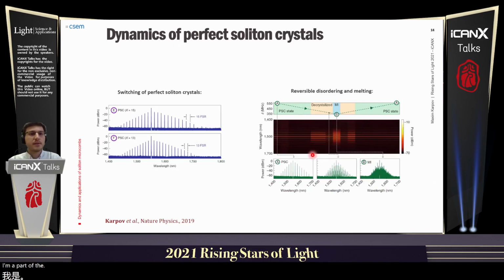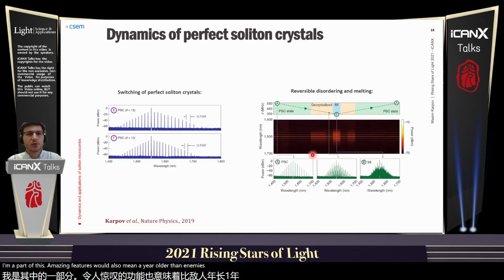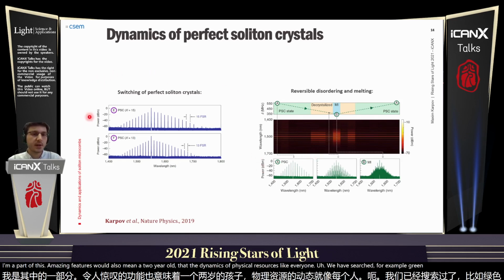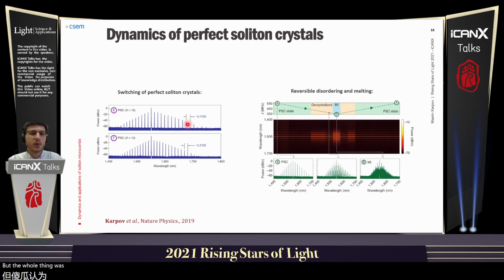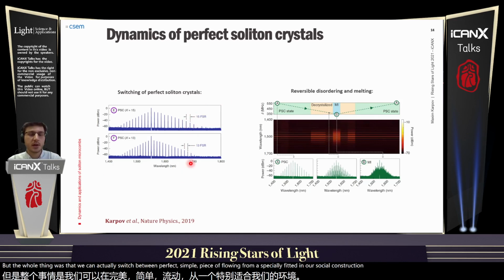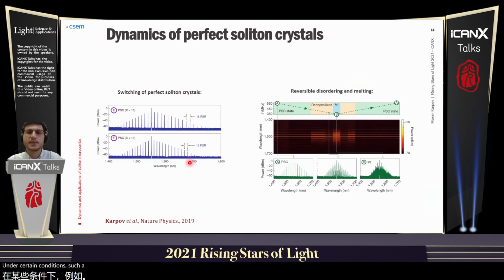Apart from having these amazing features, we also figured out that the dynamics of perfect soliton crystals is quite peculiar. We observed, for example, the switching of these perfect soliton crystals, as for the regular soliton states. But the cool thing was that we can actually switch between perfect soliton crystals, going from a soliton crystal with 15 solitons to 13 under certain conditions, if you properly treat the system.